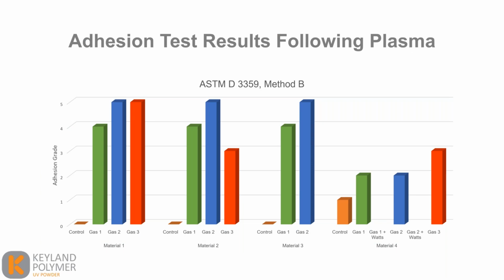So what I'd like to draw your attention to in this slide is the impact the process gases have on adhesion levels. So you can see the difference between gas 1, 2, and 3 on all of these materials. So it's not only the plasma treating process, but it's doing the little bit of research needed to determine which process gas is the ideal gas for that substrate. Another important thing to note is that if wattage is increased in the chamber, this can sometimes improve adhesion as well. And in this example on material 4, we see a doubling of adhesion.